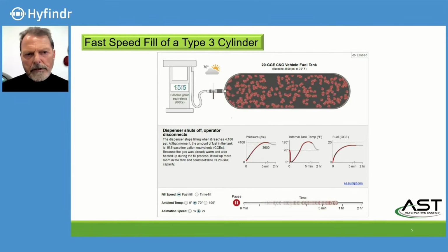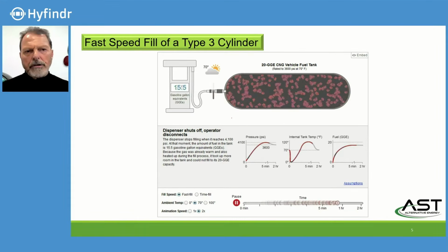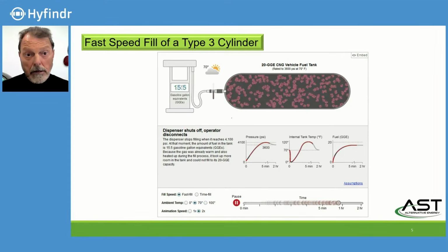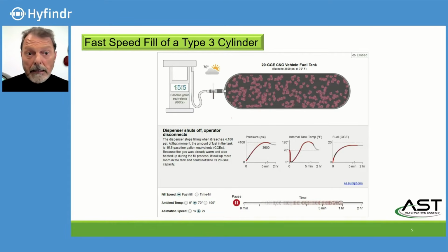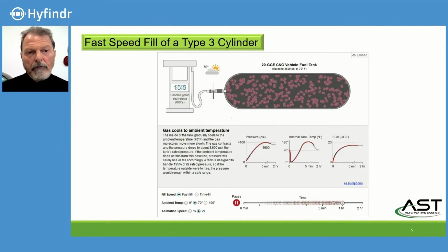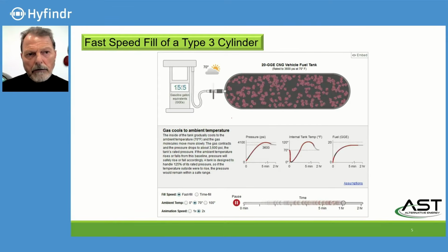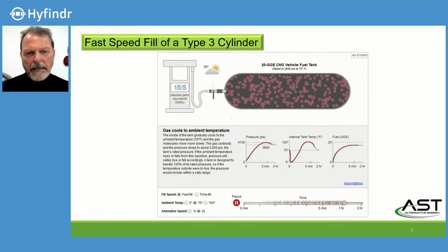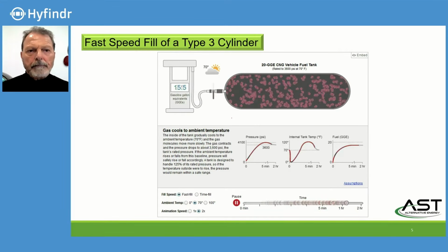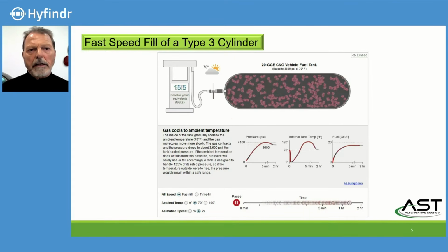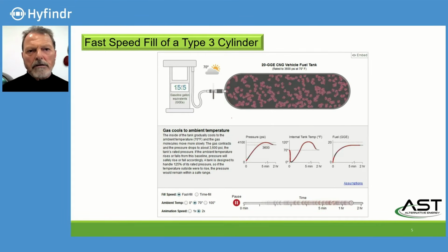And then on the right graph, you can see you have not reached 100% fill. So what happens now, when you see the bottom graph, the temperature starts going down. So it's cooling off slowly, and then I can refill if I have to on the type 4. But on the type 3, I don't have that because that heat is getting into the liner. Okay. So therefore, when the molecules heat up, the heat goes into the liner, and I can get a better fill. The heat is not trapped in the tank. Okay, so I think that's a considerable advantage.